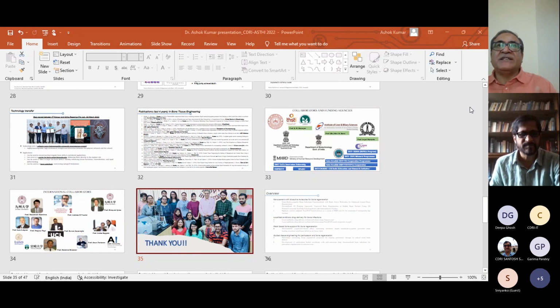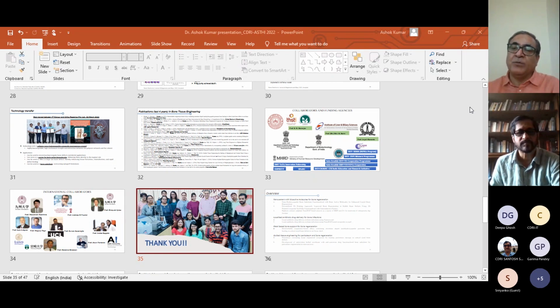Of course, periosteum in most cases, if the defect is not so large, as you are also aware, it's called the bridging of the corners in the bone. When the bone bridging happens, the periosteum also starts growing in that manner. But if that becomes a sort of limitation, you get the trabecular bone, you get some part of cortical bone growth, but then the upper part is not complete, you don't have the bridging of the bone on the top. So then the periosteum becomes the limited part.